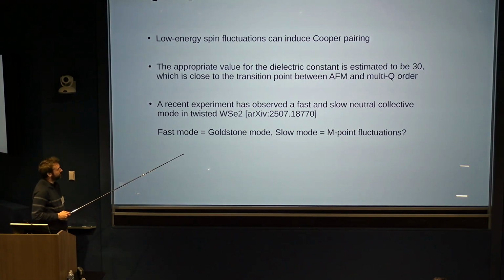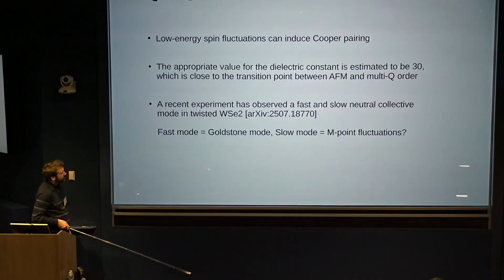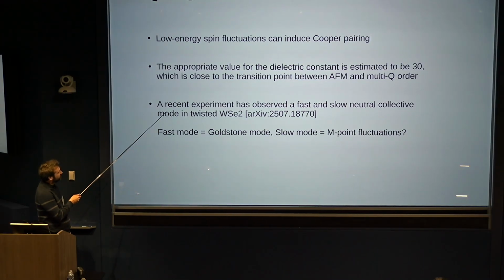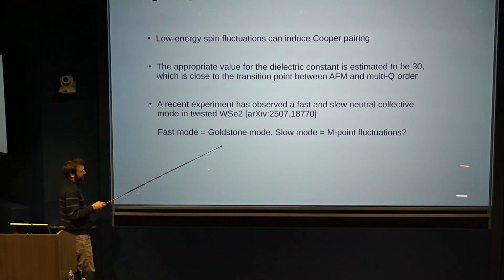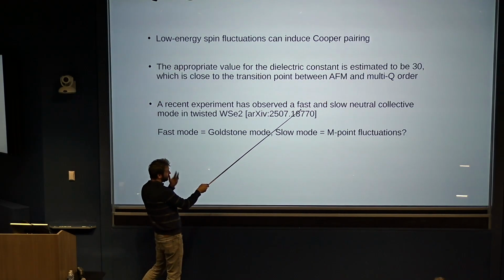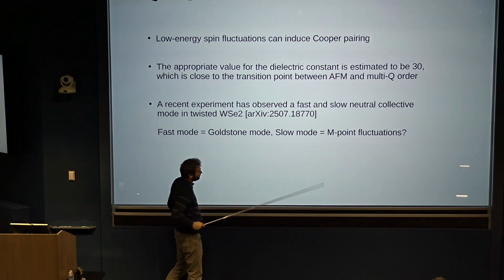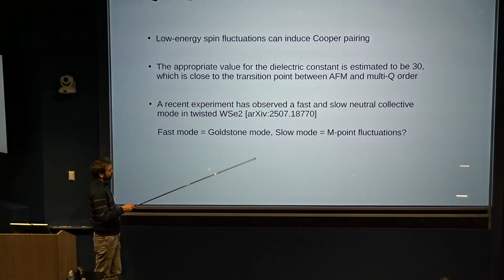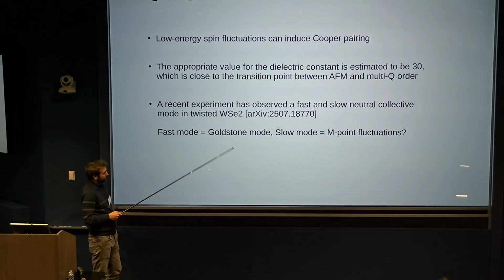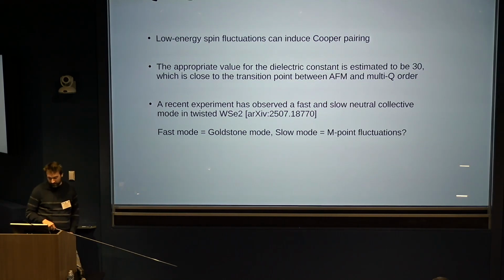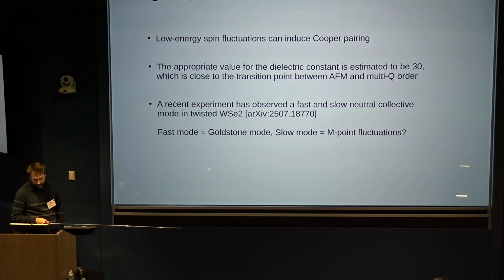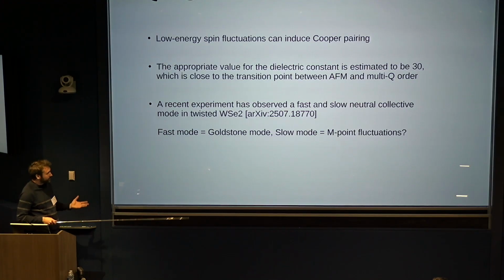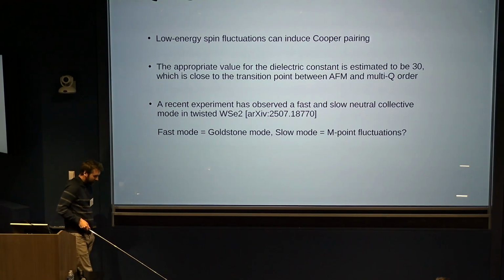Another reason that I'm pretty convinced that these modes are there is that I think they've actually been seen in experiments. There has been a recent pump probe experiment looking at collective modes. And they saw clear evidence for a fast neutral collective mode and a slow neutral collective mode. So the fast mode was interpreted by the experimentalists as the Goldstone mode, the spin wave of this AFM. And I think that's a pretty convincing interpretation.